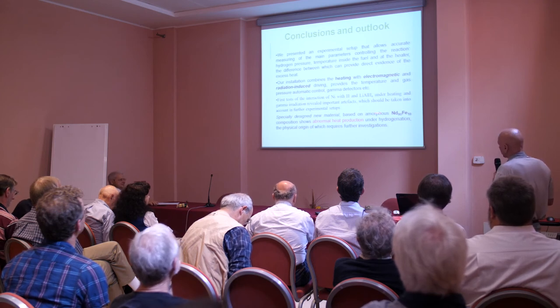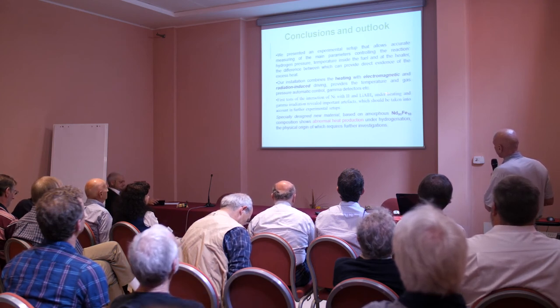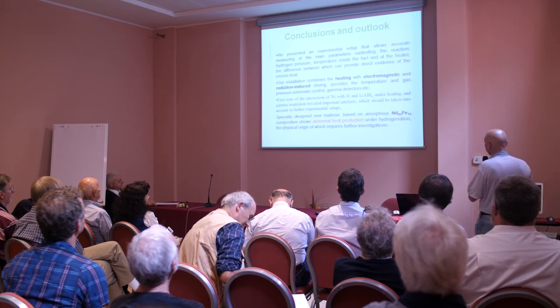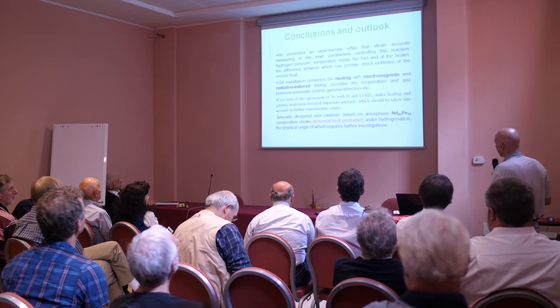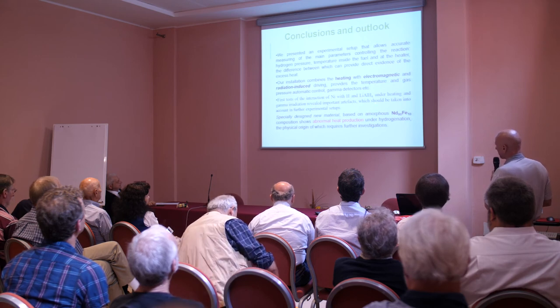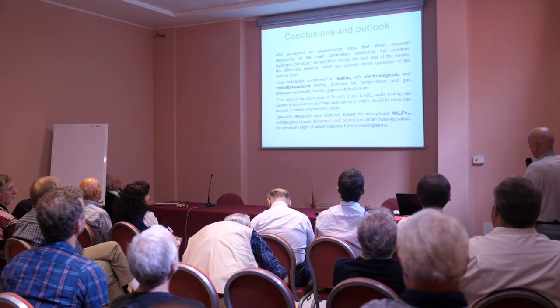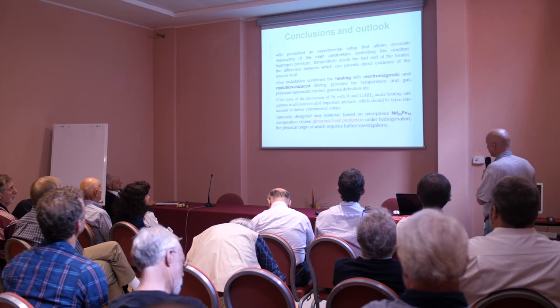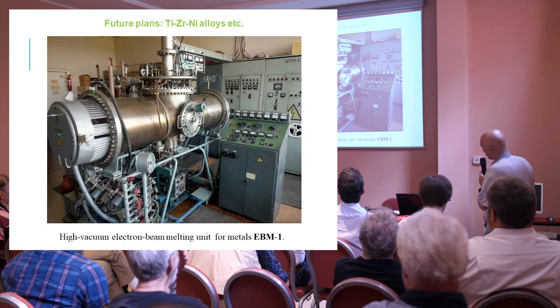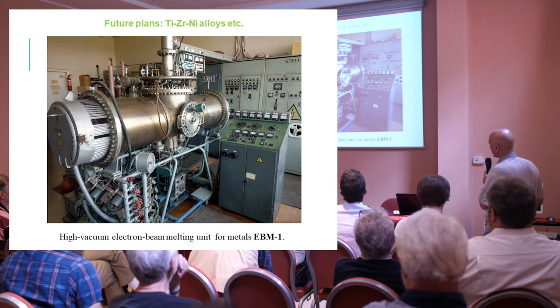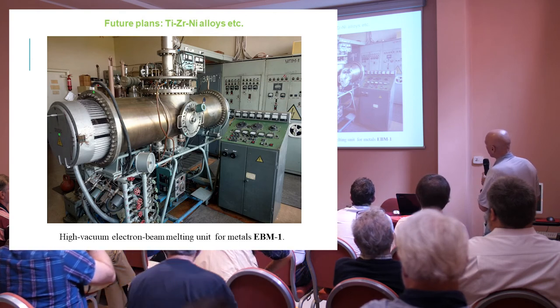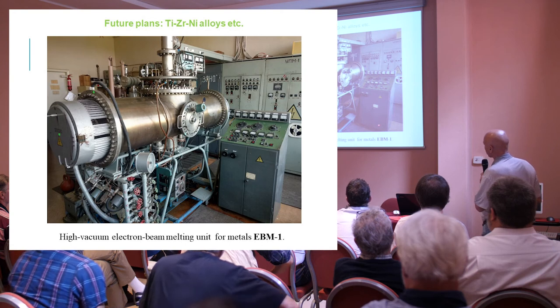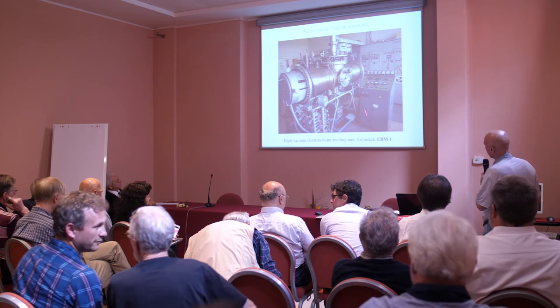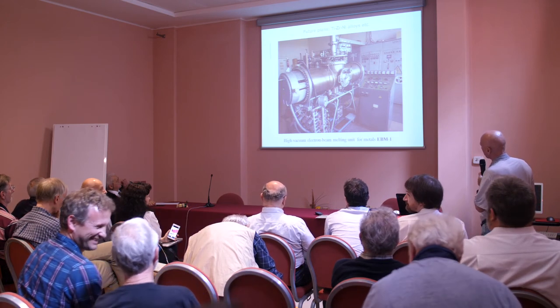And the first tests indicate that the experiments with lithium hydride should be continued because so far we encountered with some artifacts, and in some other experiments, materials will be and are actually synthesized. Now, in another types of installations that we have at our disposal, like for instance electron beam melting, promising is this titanium, zirconium, nickel, but this is a future story.